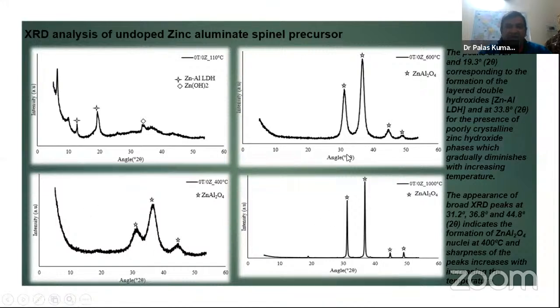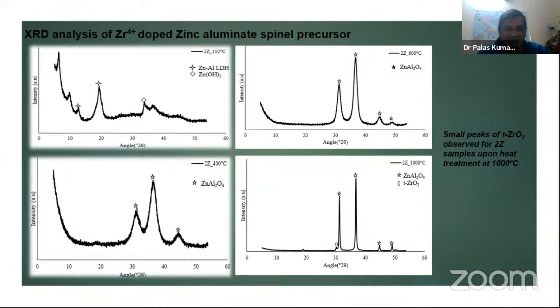This is quite obvious. And if we see the zirconia doped analog, the same zinc aluminum layered double hydroxide is formed at the lower temperature in the heat treated sample, and with increasing temperature this also diminishes. But here, at 1000 degrees centigrade, there is a peak of zirconia, which is isolated. This is tetragonal zirconia. Sorry, there is another very small peak, not shown, around 34 to 35, which is also a secondary peak of tetragonal zirconia.